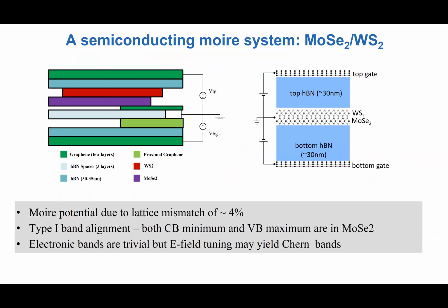I will show you rather quickly the real part. This is now a more complicated system where I consider a bilayer. I do not introduce a twist angle because these two materials have a lattice mismatch, of about 4 percent. If I consider the regime where the molybdenum atom sits on top of the tungsten atom, the so-called MM site, because of the lattice mismatch, these sites would reproduce themselves every 8 nanometers or so, even if I do not have a twist angle. If I introduce a twist angle, I can change that, make it smaller. But I have this Moire lattice irrespective of the angle, okay?